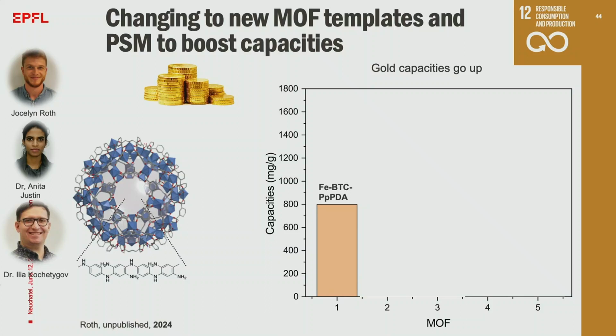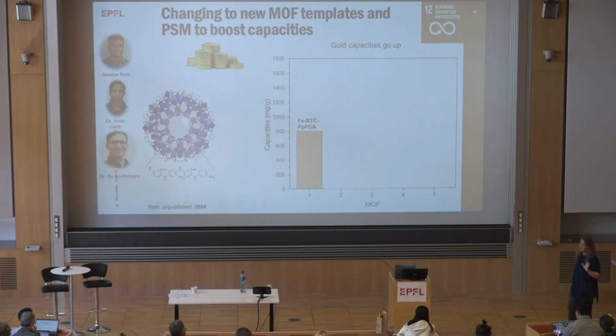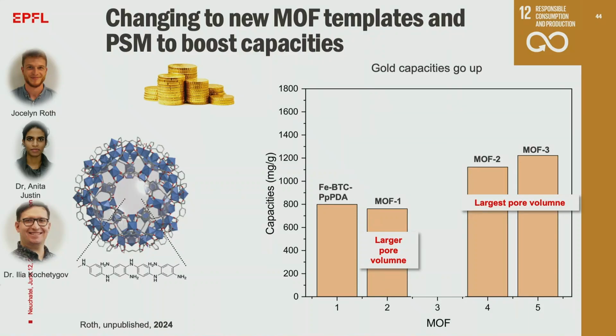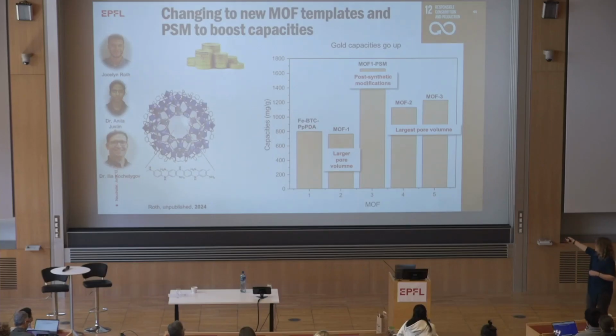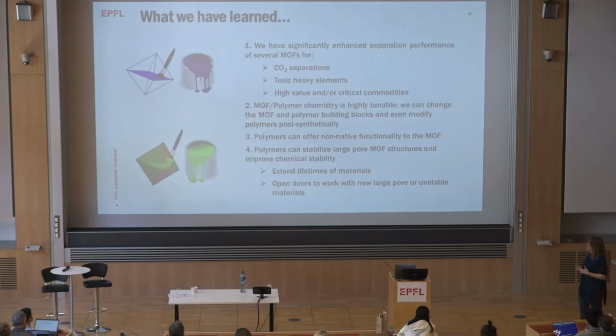So here is our original MOF polymer composite for gold extraction. If you remember, the MOF itself had a capacity of around 136 milligrams per gram, so down here. After we modified it with PpPDA, the polymer, it jumped up by a factor of 4 to 5 times. Now when we go to larger pore MOFs without the polymer, look at our capacities. Already we're above that of the iron BTC PpPDA. And then when we add polymers inside of these materials, we can physically just get a lot more inside. It increases our capacities, and you can see that we've already been able to double that original value.